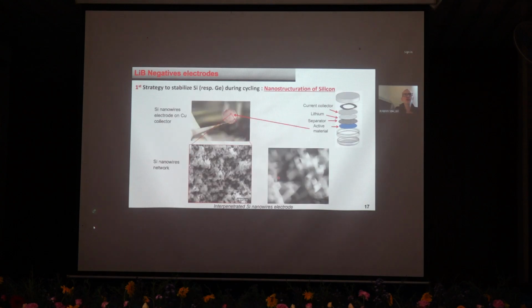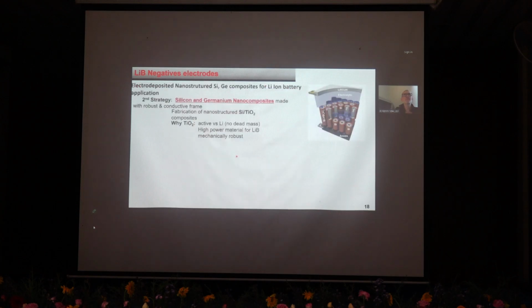So in the past, we tried in the lab to create a nanostructuration of the silicon by growing an interpenetrating network of silicon. We had quite a good capacity, very promising, but the material cycle life was limited due to the poor electrical contact between the silicon and the current collector. So then we switched to composites, which is the main interest right now of the technique we have developed.